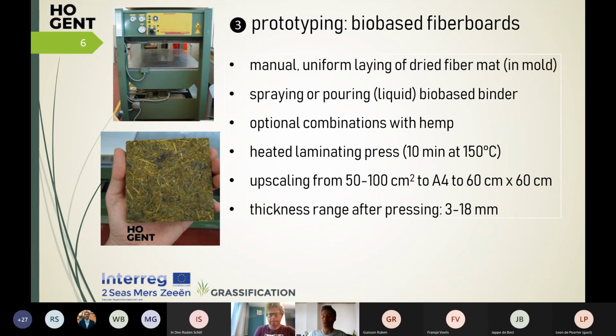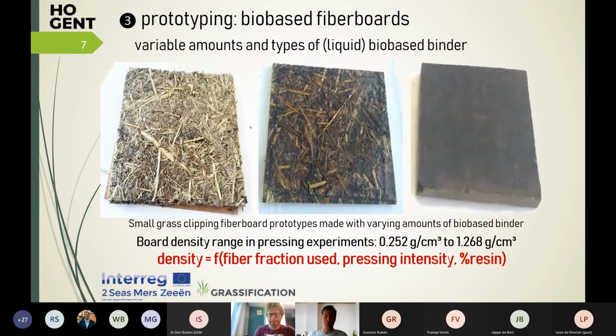The thickness ranged between 3 and 18 millimeters, the latter being the commercial thickness of wood-based panels. Here are shown some examples of these panels. So we had lightweight panels and more dense, heavy panels. The density ranged from about 250 to 1,250 kilograms per cubic meter, depending on the amount of resin that was used, which type of fiber fraction was used, coarse or finer grass, and of course on the pressing intensity, which was also visible in the variation in the thickness of the panels.